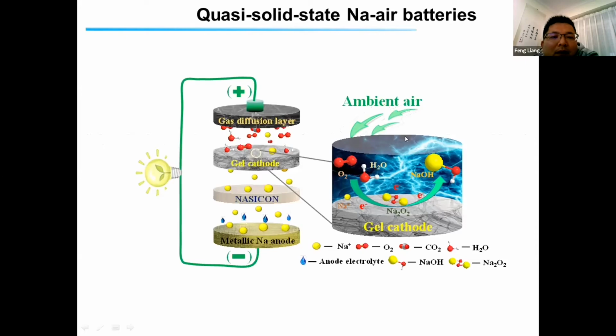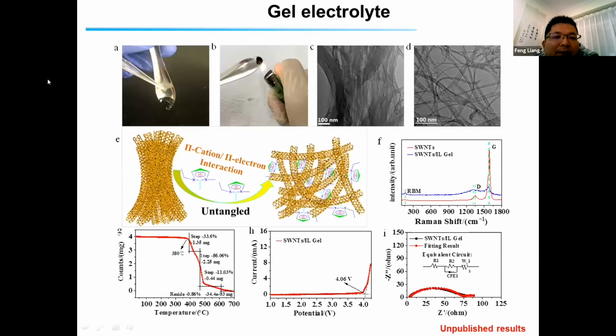for a long time. And firstly, I will introduce how to prepare this gel electrolyte. So this is a reaction, just the interaction between the single wall carbon nanotube and the ionic liquid. So after the pi cation and the pi electron interaction, the single wall carbon nanotube was separated, and then we can get this gel. It is hydrophobic. Also, it couldn't be fired. Also, this gel has good stability and a very large electrochemical window.